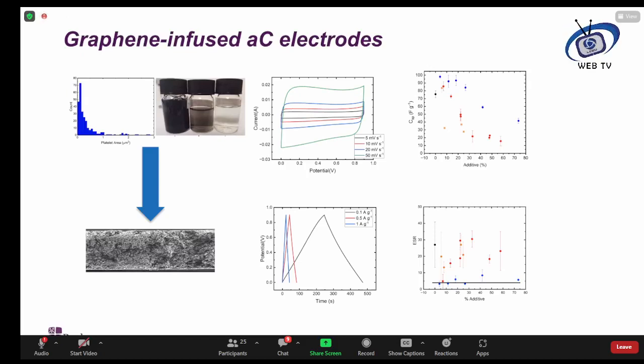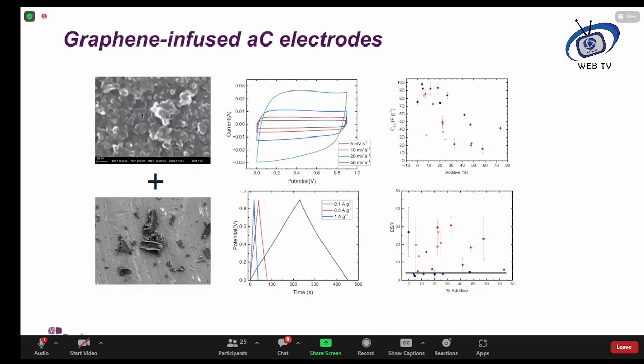that we tried. And finally, we compared with just adding a standard conductive additive, which is Timcal C65, which is shown on the SEM image over here, with the activated carbon shown on the image below. And this is our kind of standard electrode configuration. And these are given by the black squares. And you can see that, again, at all compositions, there is an increase in performance associated with the broad distribution of graphene platelets.